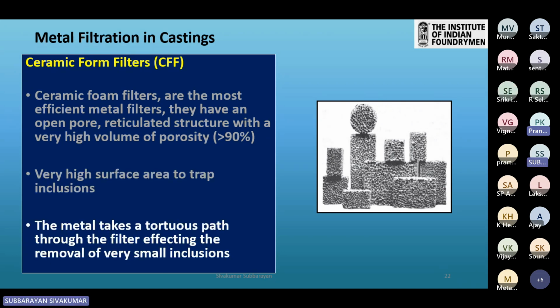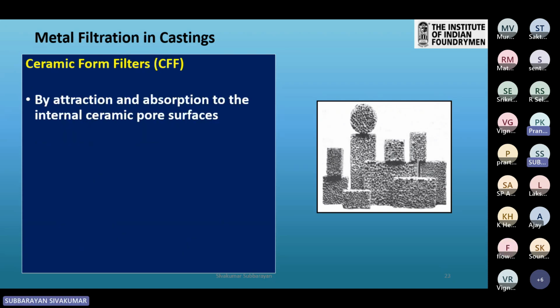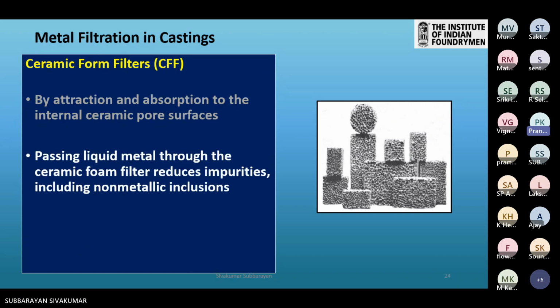The metal takes a tortuous path through the filter, affecting the removal of very small inclusions. So, being the honeycomb structure, once the metal enters one side of the filter, by the time it comes out, it has to travel through a very difficult path. So, in that, all the impurities are being filtered. That is one of the main reasons for the success of these ceramic foam filters. By attraction and absorption to the internal ceramic pore surfaces, the filtration happens. Passing liquid metal through the ceramic foam filter reduces impurities, including non-metallic inclusions.